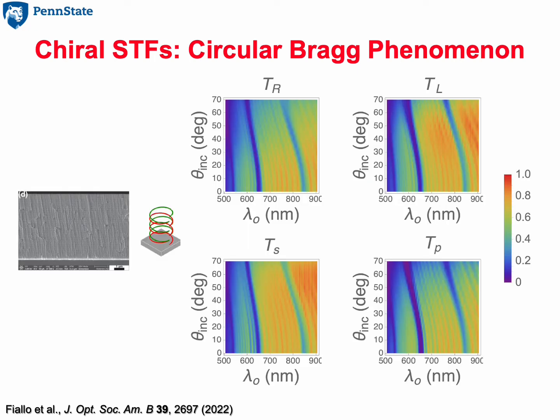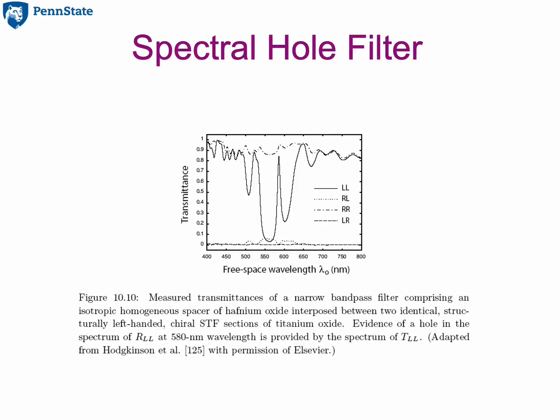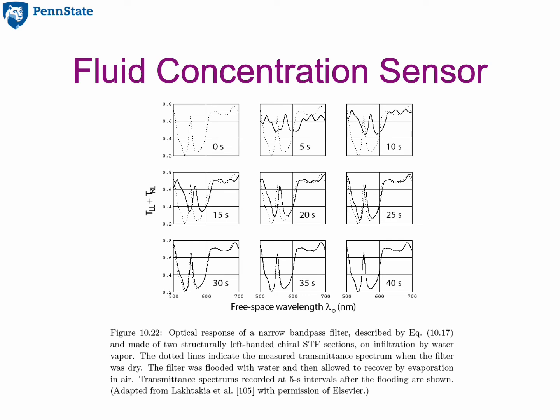We can now make band stop filters that are independent of the polarization state of the incident light, as you can see by the blue bands, by the very dark blue bands in all four of these transmittance spectrums. An important type of band stop filters is the spectral hole filter. If the center of a chiral sculptured thin film has a 90-degree twist in it, it becomes a spectral hole filter. The Bragg regime is around 50 to 100 nanometers wide, but the spectral hole is around 10 nanometers wide. The spectral hole is a very sharp feature in the spectrum.